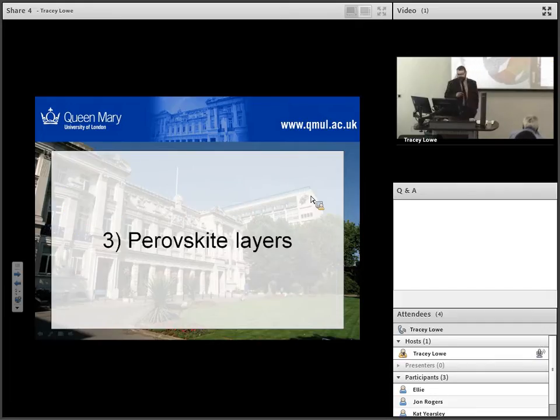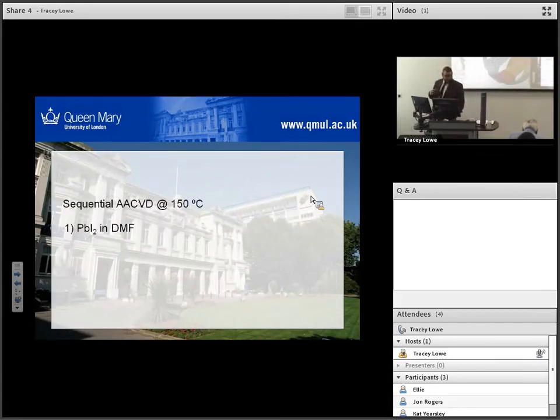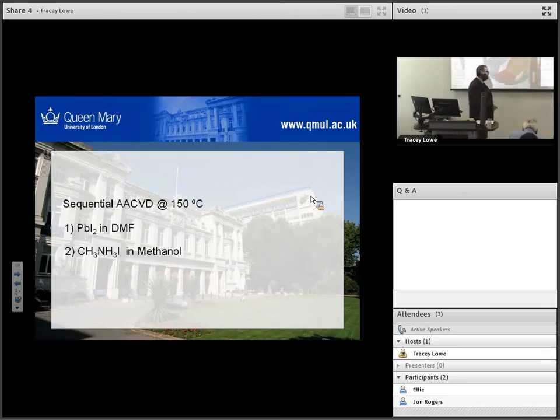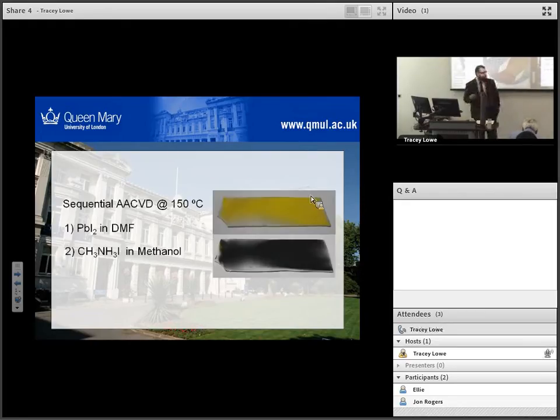Okay, final thing I want to mention then, perovskite layers. Rather than some of the stuff that I think you guys have done and Ivan Parkin's group have done at UCL, we've taken to a sequential CVD method. First reaction is to deposit some lead iodide and then have our methyl NH3 iodide in the second step. And the reason for this is we find that we get some nicer morphologies.